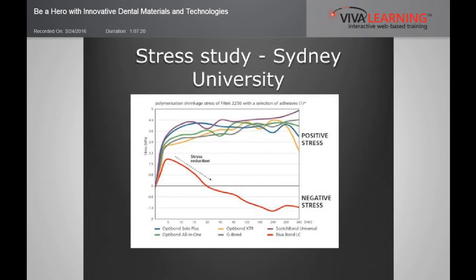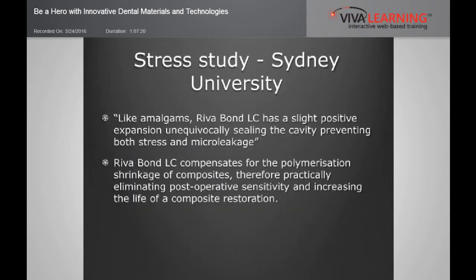Okay, we compare here Rivabond LC with many leading resin adhesives on the market. I don't say that those adhesives are not good, but that's another product. And the idea, after 30 minutes, we don't have any stress at the interface of our restoration. And in fact, we get a slight positive expansion of that Rivabond that will seal the cavity, preventing both stress and micro leakage. So the idea is that with that Rivabond, you have an adhesive that compensates for the polymerization shrinkage of composite.